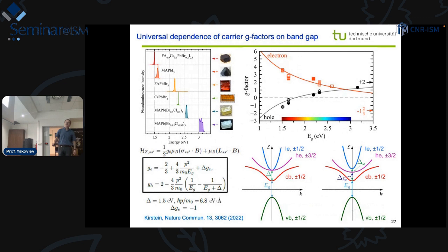What we do, we study different perovskite materials, single crystals are shown here, where the band gap is changed from 1.5 electron volt up to 3.2 electron volt. So here are more chlorine-based, here are iodine-based materials. Some of the materials are nearly cubic, so it's sufficient to measure one component. But some of the materials, like for example MAPI and cesium lead bromide, are anisotropic. So we need to measure all directions and also take into account that g-factors can be anisotropic.